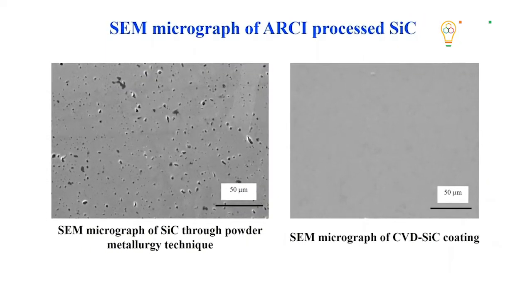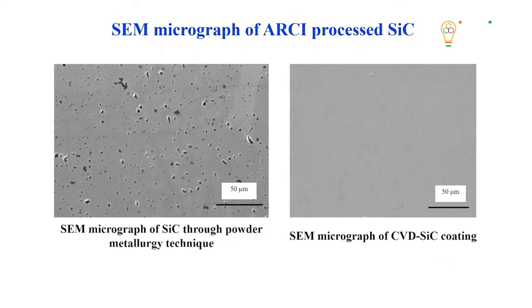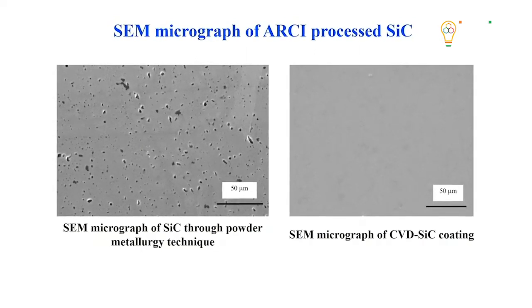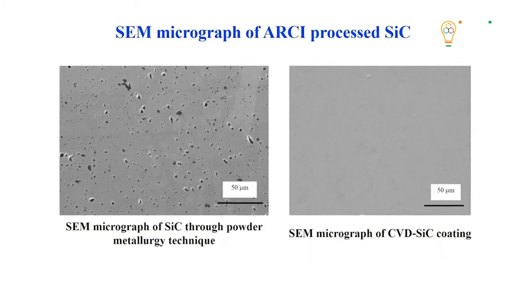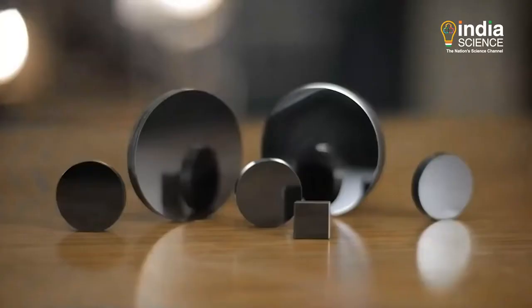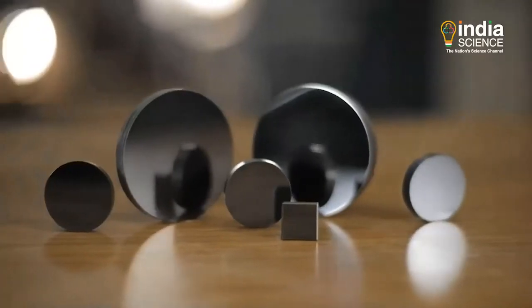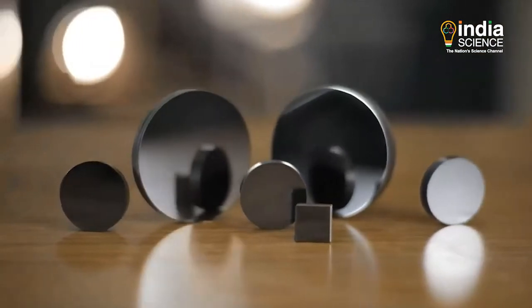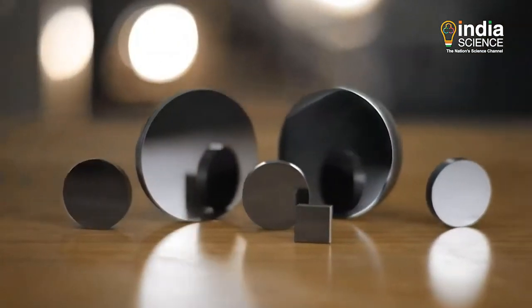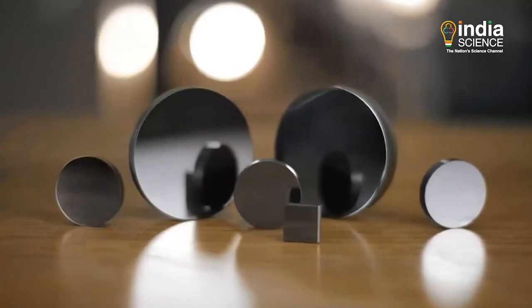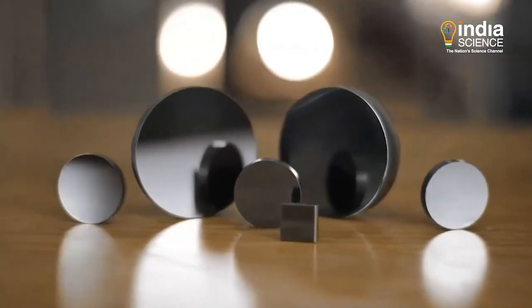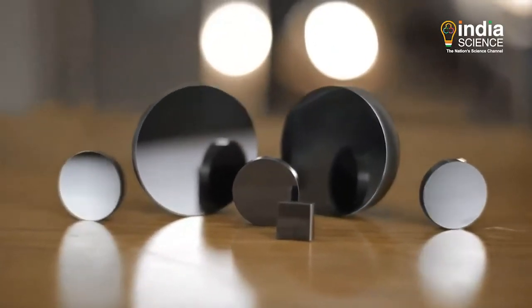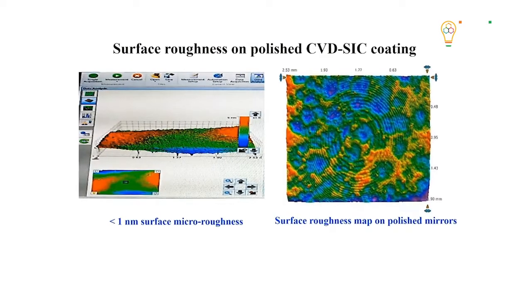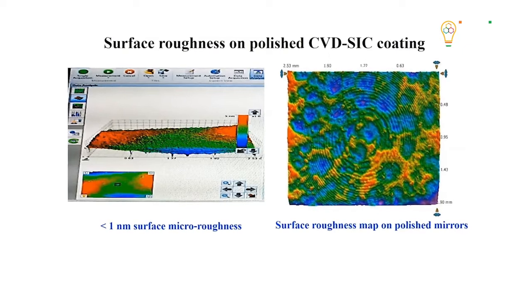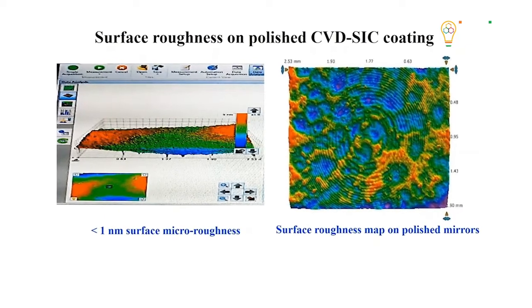To use these substrates as reflecting surfaces, a dense coating of silicon carbide is applied through chemical vapor deposition. This removes the non-uniform microstructure of these components as well as the residual pores. Reflecting surface is then generated through surface grinding, diamond paste polishing, and ion beam polishing. In this way, a surface roughness of less than 1 nanometer is achieved, which is quite remarkable.